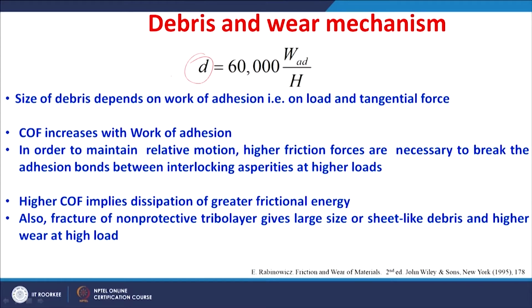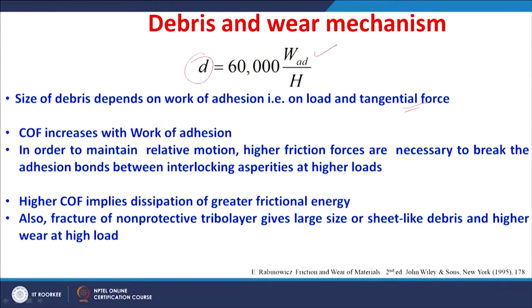The tribochemical wear actually resulted in sheet-like debris of a larger size, around 50 to 100 micrometer. We can also understand this with the adhesion theory. The size of the debris can be related to the work required for the adhesion to happen. The work of adhesion means the load as well as the tangential force, so you can see the coefficient of friction involvement here. In fact, the coefficient of friction increases with the work of adhesion. The larger the work of adhesion, the higher the coefficient of friction.